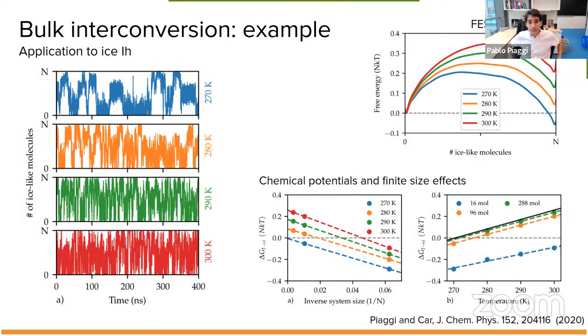Now I would like to show an example of the things that one can do with these ideas. So if we do a simulation, say in this case of ice 1H, and we bias this collective variable, the number of ice-like molecules, we will see trajectories like the one that I'm showing here, if we constructed a good bias potential. And this is shown for different temperatures, and you see that at high temperatures, it works really well. As we go to low temperatures, the simulations become harder, but still they work reasonably well.